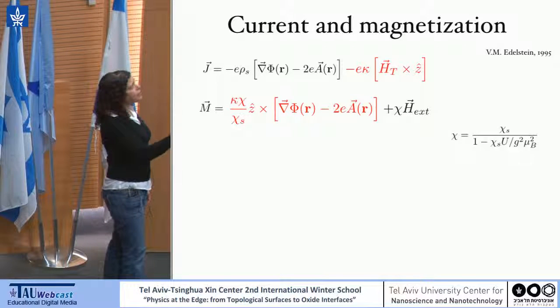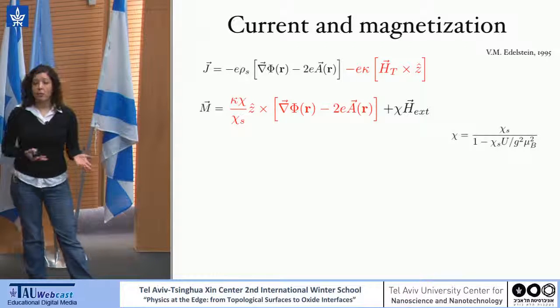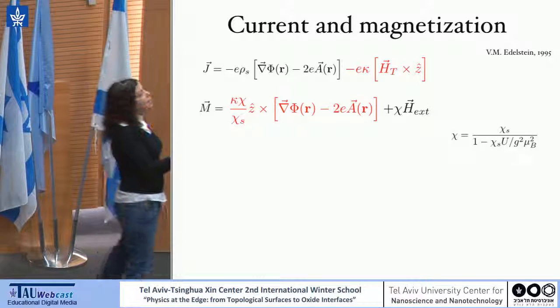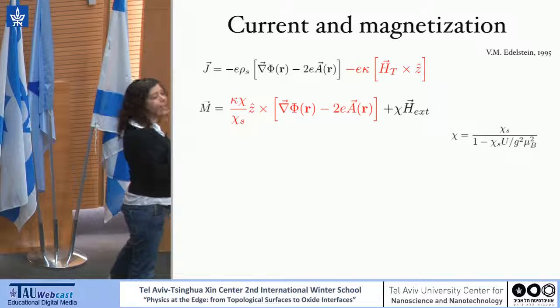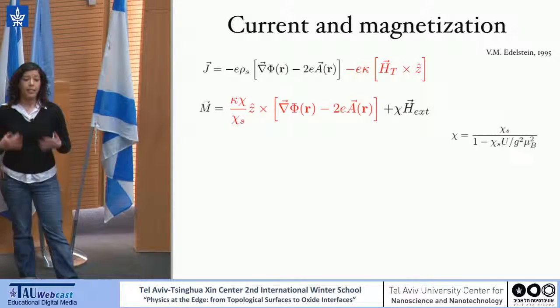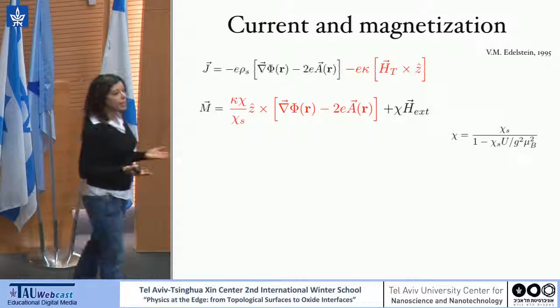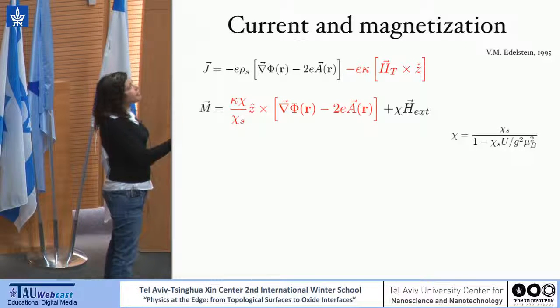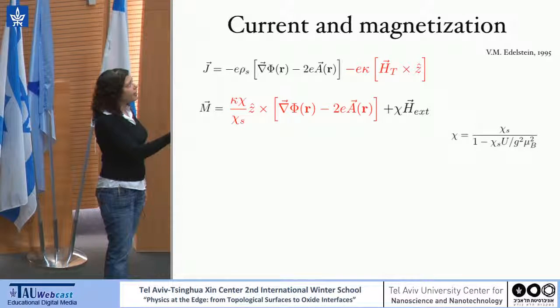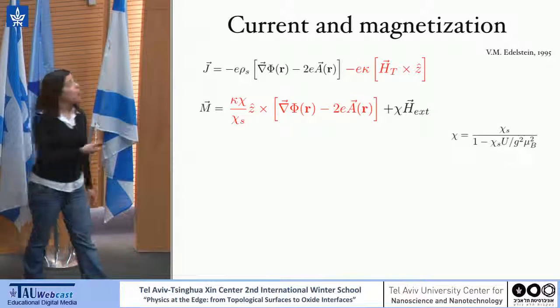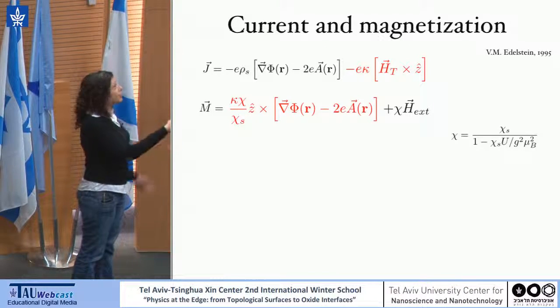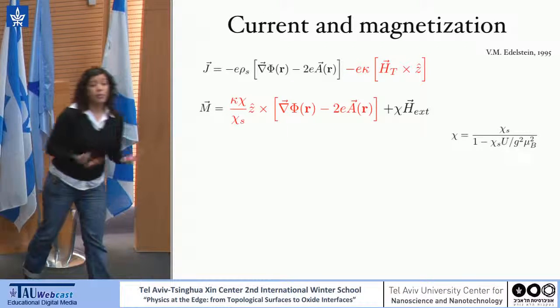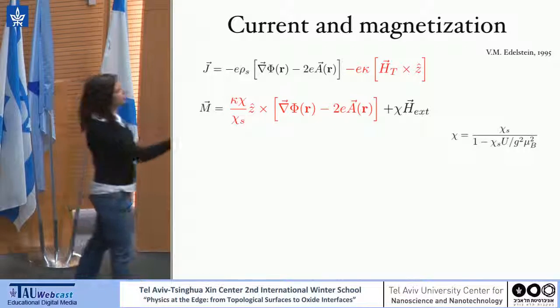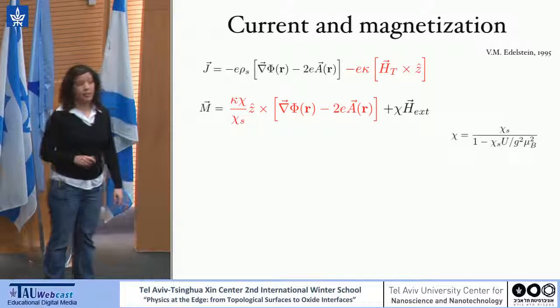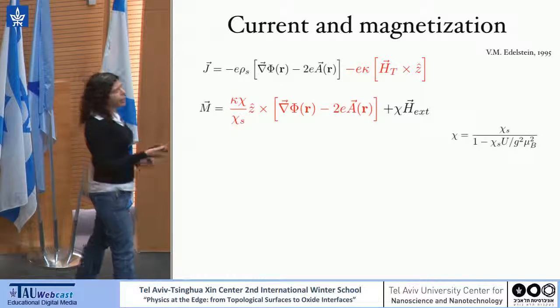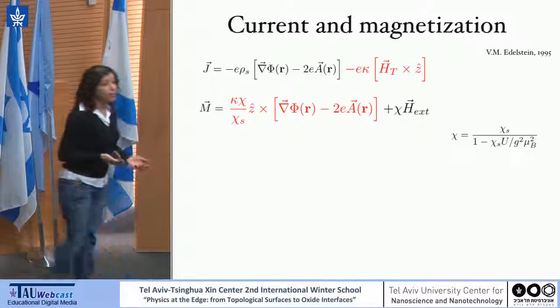Usually, the superconducting current is just proportional to the gradient of the superconducting phase. However, now we have an additional contribution that is coming from the magnetic field, again either magnetization or external magnetic field. In turn, when we look at the magnetization of the system, it has two contributions as well. One is proportional to what is usually the current, the gradient of the phase, and the other is the regular spin susceptibility times the magnetic field, which in a regular superconductor again would be 0, but here is non-zero.